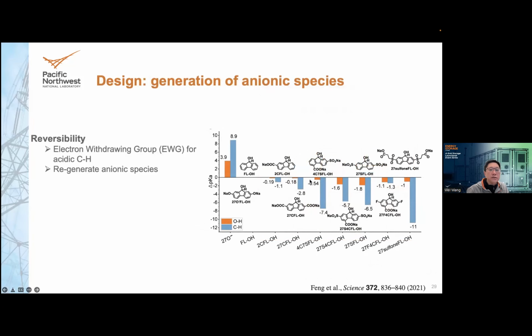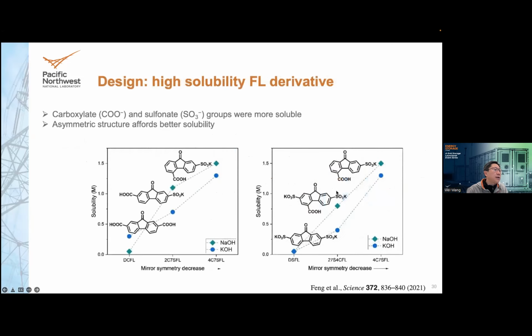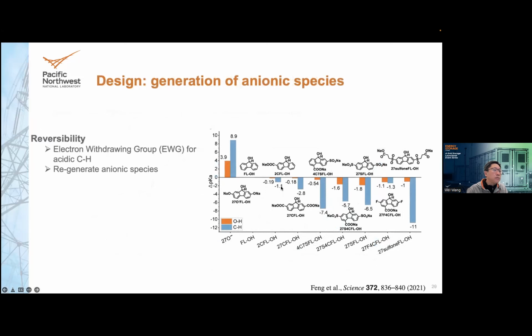They can go through some kind of redox reaction, but not fully. So what we found is that this is basically caused by the protonation. So we came up with a strategy to decrease its tendency to protonate, by lowering the pKa to make the material easier to deprotonate, to generate those ionic species. So we did a whole series of studies on putting on different electron withdrawing groups that will make the proton easier to go away. And we identified that by adding electron withdrawing groups, you can lower the pKa of both the OH and CH. So both protons can be deprotonated, which contributes to a 2-electron reaction.